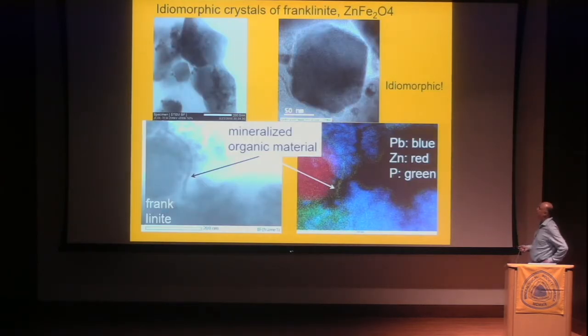What we also observe is perfectly idiomorphic crystals of franklinite growing nicely within amorphous matrices. And when you take a look here, we have a franklinite crystal, and it's perfectly grown, aligned to a mineralized organic matter. We have here in green phosphorus. So we have here the string of former organic material, and this spinel crystal has been perfectly aligned and grown along the organic string shown here.